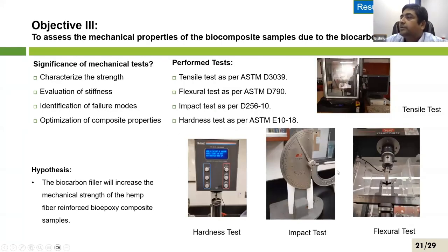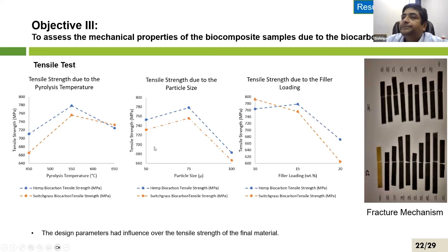And then we looked at the mechanical properties of these composites. We looked at the effect of temperature, so 450, 550, 650. What we found is, the one that is carbonized around 550 gives the maximum tensile strength. Similarly, particle size 50, 75, 100. If you go to a larger particle size for the biochar, its mechanical properties go down. And the dispersion is the main problem.